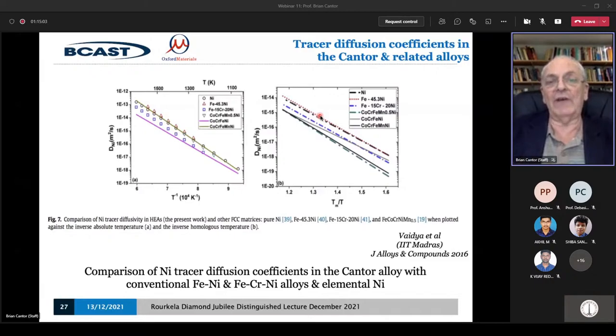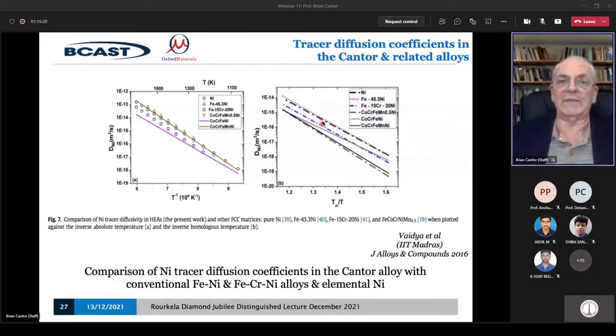But if you have a Cantor alloy, then this local strain opposes the atoms moving around and jumping into the vacancy, because the strain fixes them in place. So their ability to move around goes down. And that's shown here. This is the diffusion coefficient measured. It's normally plotted as a function of 1 over temperature. So this is high temperatures, this is low temperatures. So the diffusion slows down.